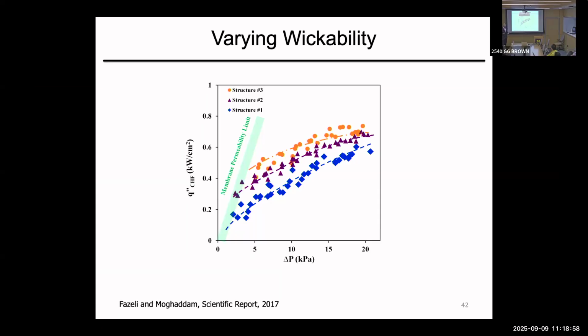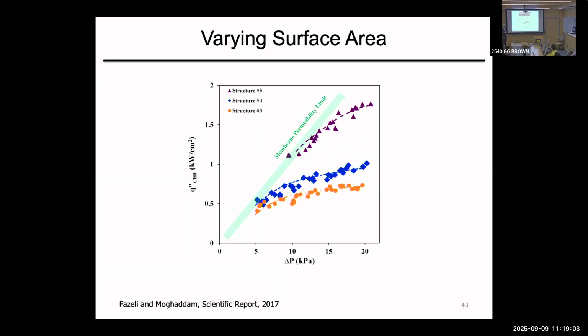So when we reached that number, we asked why they came up at roughly the same number. And you say, because they have the same surface area, right? Okay, now let's keep the capillary constant and increase the surface area. As we increased the surface area, we went right back to marching up in CHF, meaning this phenomenon was surface limited. We squeezed the bubbles out, we squeezed the liquid in, and the CHF increased, but we capped out because all the surfaces had the same surface area. Now, when we increased the surface area, we saw a direct relation between the surface area and the CHF.